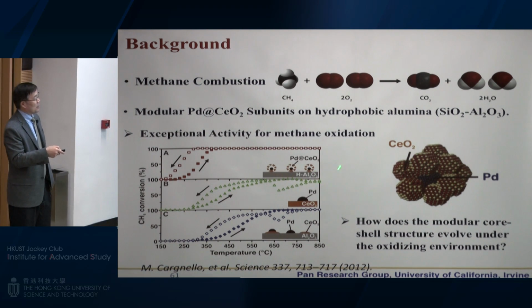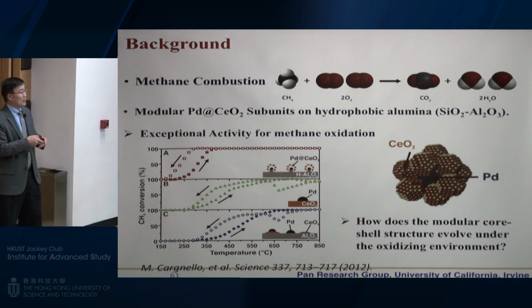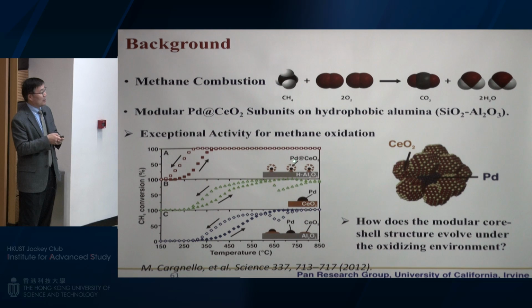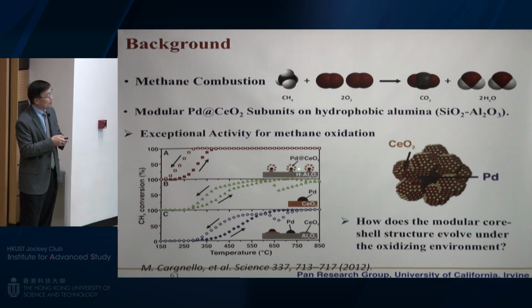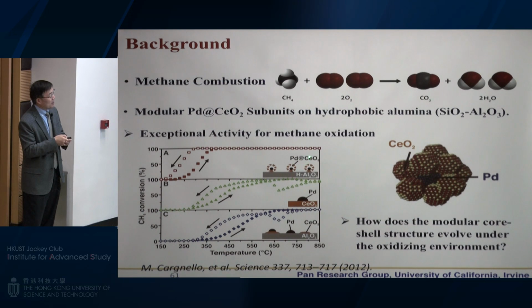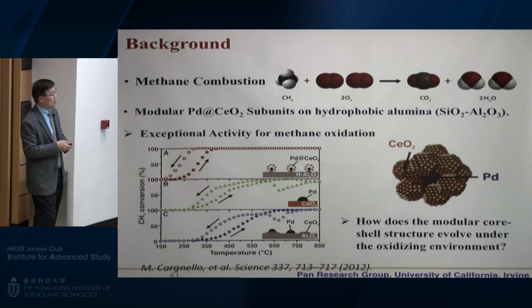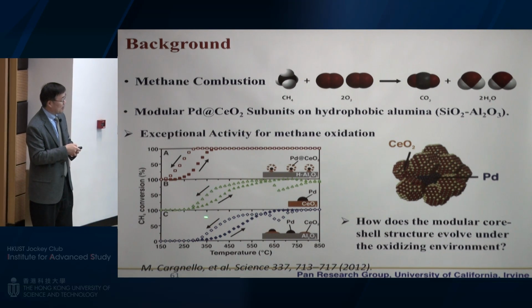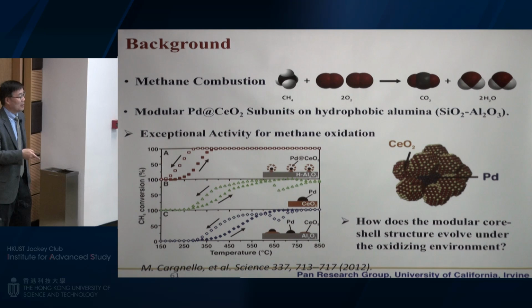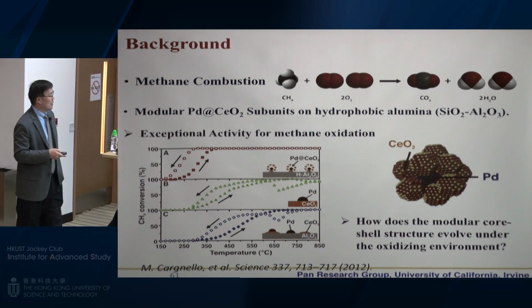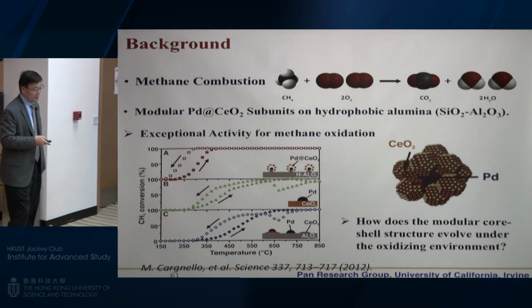But then he developed what he called the core-shell catalyst. It has a palladium core, surrounded by ceria oxide particles that he called the shell. He thinks this kind of core-shell structure is critical for the improved catalytic activity. His catalyst can have a very high activity at even 200 degrees C, which is significantly lower than the traditional catalyst. He published this work in Science about 3 or 4 years ago.